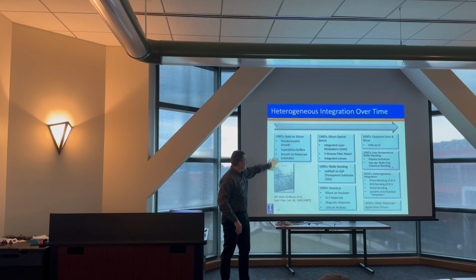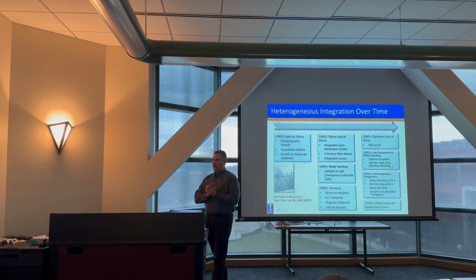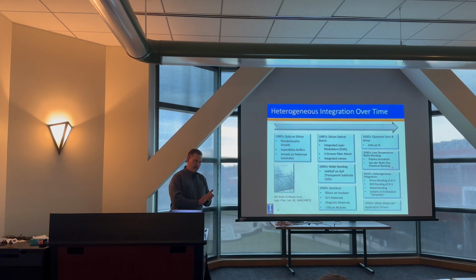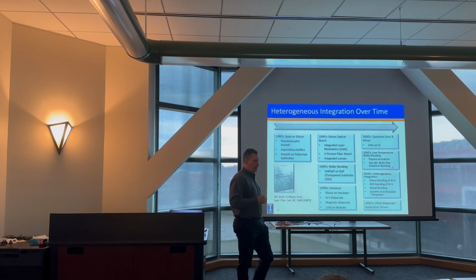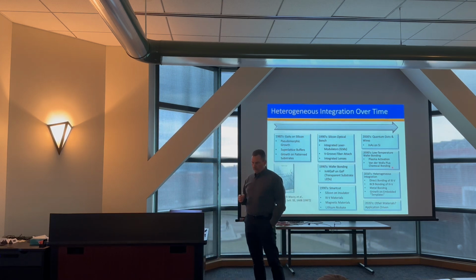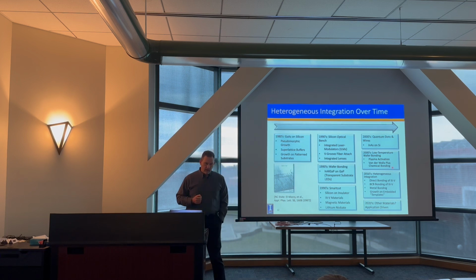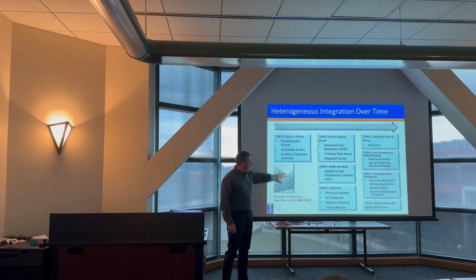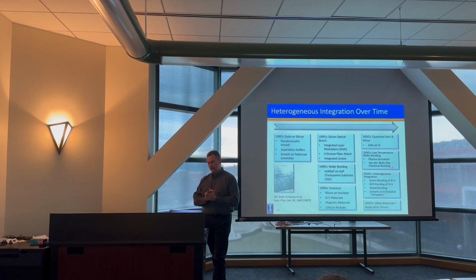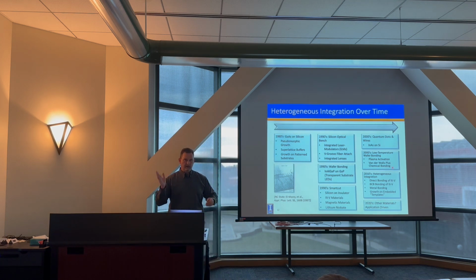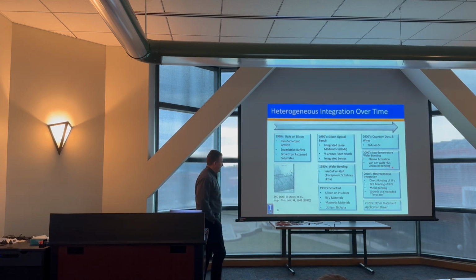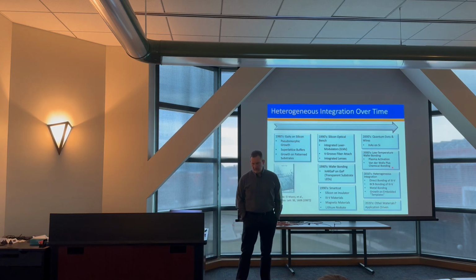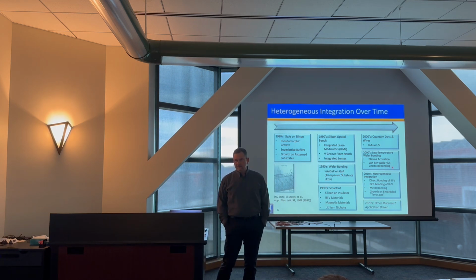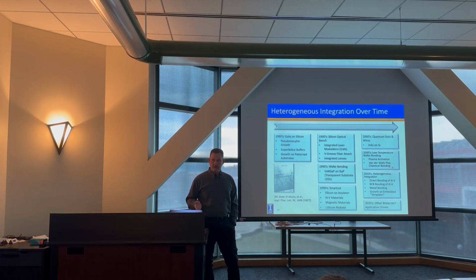In fact, if we go back to the 1980s, back to when a lot of the growth technologies we use today, MOCVD, MBE, were really being worked on very aggressively. People tried doing direct growth of 3-5 materials on silicon. In fact, back when I was in Nick Holonyak's lab in the 80s, we had people working on gallium arsenide based lasers on silicon, okay? And you could make a gallium arsenide based laser on silicon.